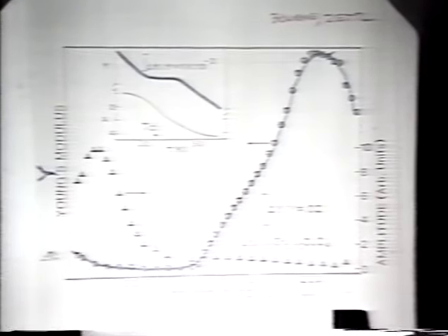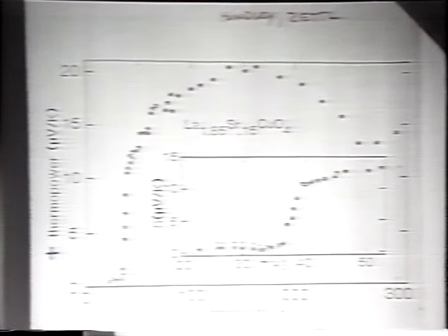We've looked at elasticity. This is measuring Young's modulus in this material as a function of temperature. We have a soft phonon mode, indicative of a tendency to structural phase transition. At TC, there's a discontinuity in Young's modulus, which can be related to the specific heat. Some transport measurements. Here's Hall effect as a function of temperature. One has a carrier density of 7 times 10 to the 21 at room temperature. There are interesting anomalies right at TC, which might be related to granular type of superconductivity. Thermopower looks very similar to what other people have measured. Thermopower as a function of temperature again goes to zero at TC and has this unusual shape for most samples we've measured.